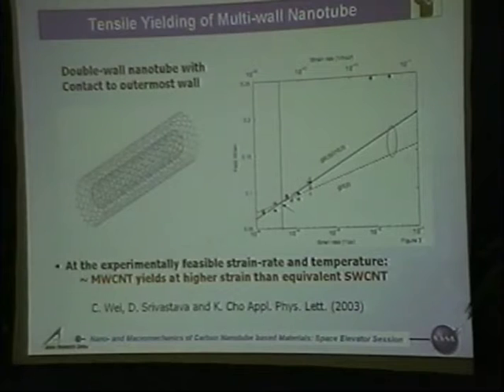But suppose this is almost like an engineering structure for a long time duration: 1 year, 2 years, 3 years, 4. What I'm showing you here is just a model, a double wall tube, which is a model of a multi-wall tube. The black line is for a multi-wall tube, and the red curve is an equivalent single wall tube. Generally the black line is better, so a defect-free perfect multi-wall tube would have tensile strength even better than single wall nanotube. These strain rates are simulated in the simulation, but these are more realistic.